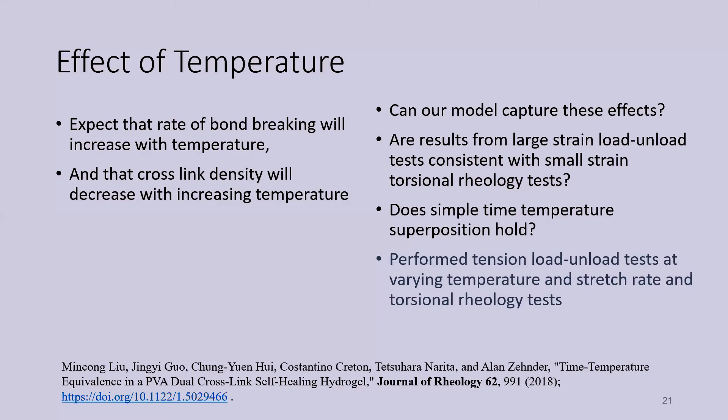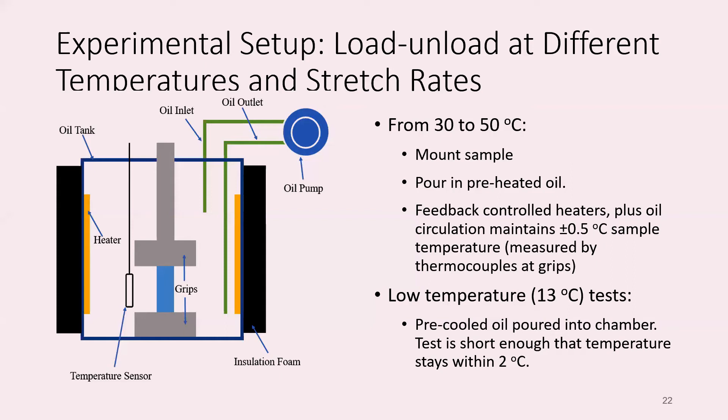What happens if you increase the temperature? We expect bond breaking to speed up, the bond reformation to speed up. We did experiments in our tension test setup and usual torsional rheology tests at very small strain. The experimental setup for loading at different temperatures is shown here. We have a thermocouple on the grips to control temperature. We have heaters with feedback control to the temperature of the oil. We have to circulate the oil a little bit, otherwise it segregates—hot oil comes to the top and we won't get uniform temperature. We're able to hold the temperature within about half a degree.